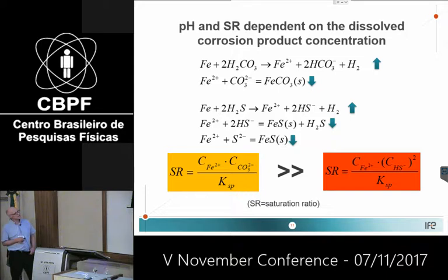And the same with H2S. When iron reacts with H2S, pH goes up because you form HS minus or S2 minus ions. And when you get precipitation, pH goes down. But there's one very important difference between iron carbonate and iron sulfide.